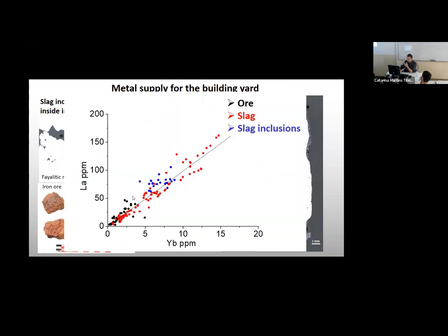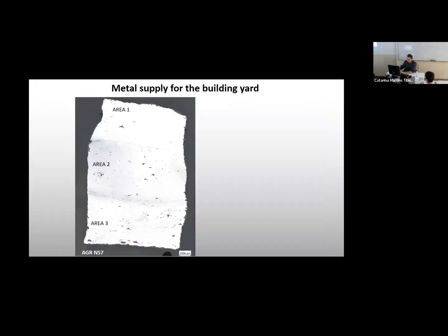And then when you make analyses of the same ore, same slag, I'll speak about this later, and slag inclusions, you have something which has the same composition, so you have one line. You would have another ore, you would have another line here or another line. This is when you get into the analysis of elements that are present in really small quantities in the matrix. So 10 ppm is 0.001%, so it's not that much. So you need to have precise means of analysis to get the information.